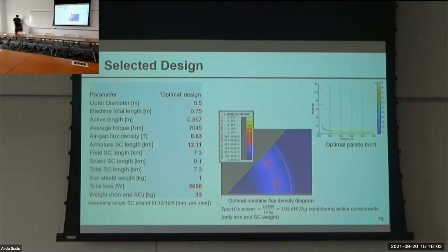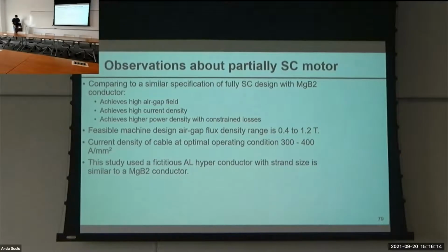This is the selected design that we looked at for the aluminum machine. And here are some comparisons with the fully superconducting machine. The performance is pretty good, and the air gap flux density can go up to 1.2 Tesla. But again, it's using an aluminum conductor that currently isn't commercially available, whereas the MgB2 conductor is available.